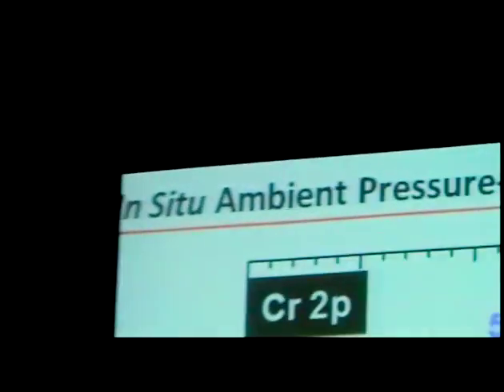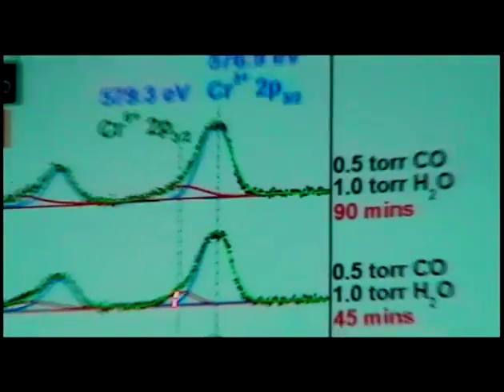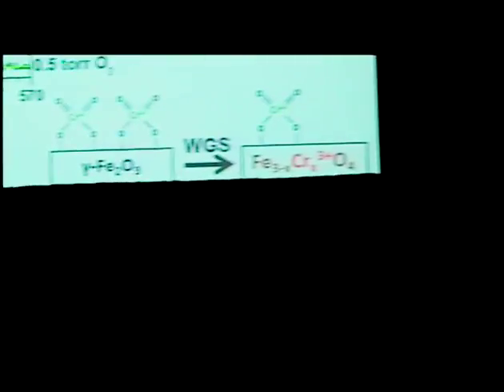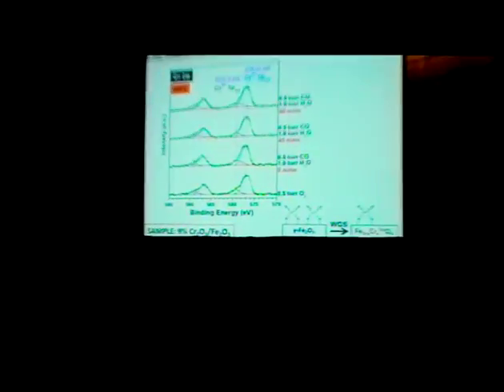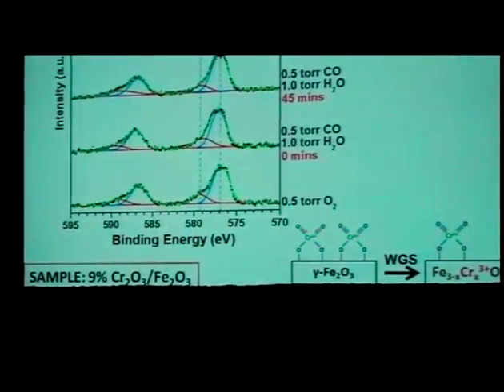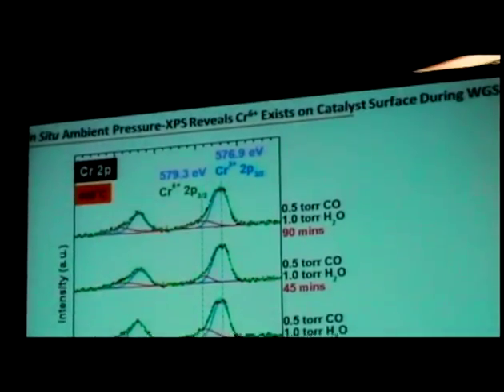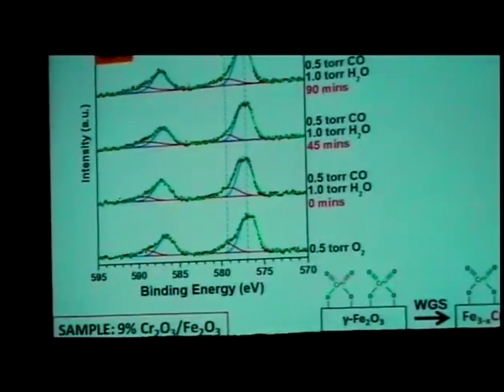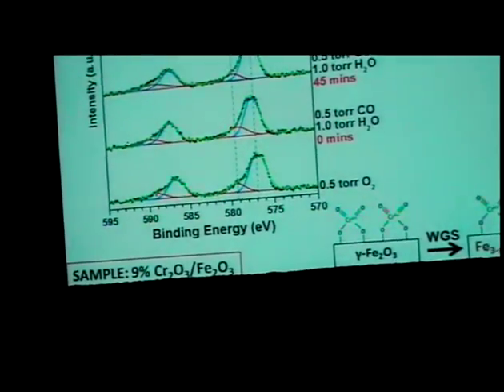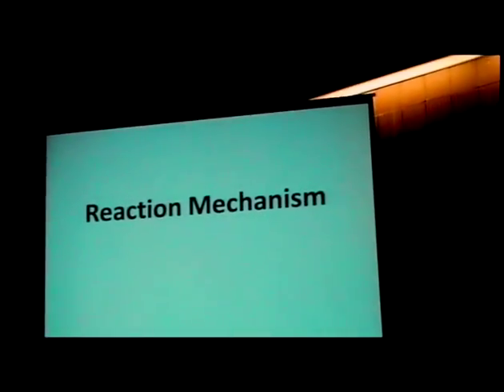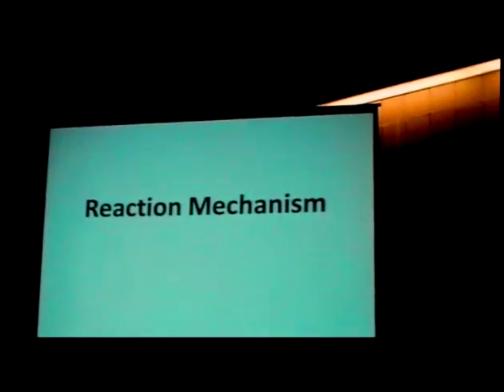And this is another study, and again showing that the chromium 6 is still there under the water gas shift reaction. This is for 9% higher loading of chromium. The previous sample was for 3% chromium. Commercial loading is about 11% chromium oxide on an iron water gas shift catalyst. So with these characterizations of the surface, I've told you what's going on with the catalyst.